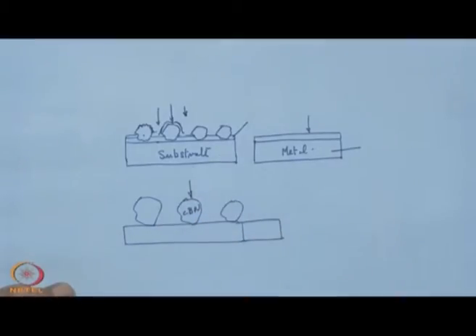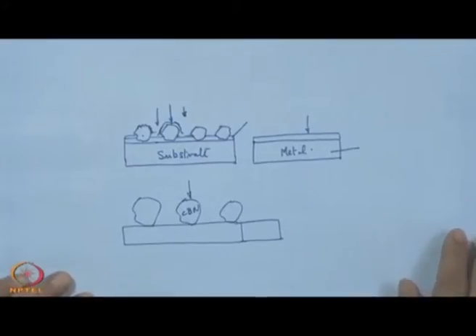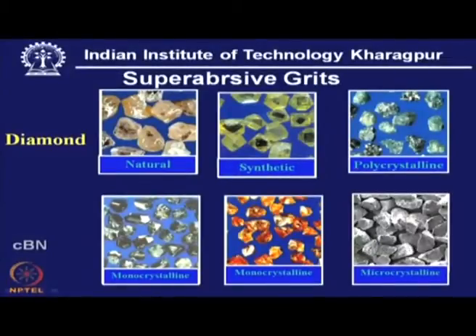So, what is to be done, and what is done also in the industrial scale, is that if we find excess boron on the surface or the surface is rich in boron, in that case something has to be done for chemical etching of this boron, and with that we can also get a little bit of micro grooves or voids over this surface. This is good in both ways.